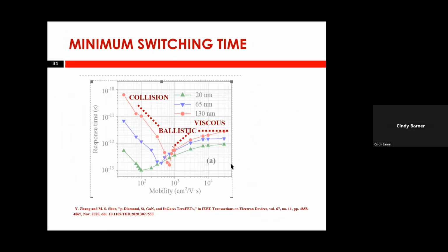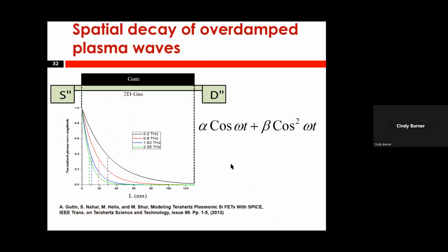And now, if scattering is too strong, then this plasma wave decays. But they take some distance to decay. They don't decay immediately. And this distance becomes shorter and shorter if you increase the terahertz frequency, because excitation immediately goes as a displacement current through the gate contact of the device. But what happens even in this regime, when you have no plasma waves, is the following. If you shine terahertz radiation on this device, the wavelength of this radiation will be much larger than the device dimensions. It would be on the order of hundreds of microns, if not a millimeter, 300 gigahertz at 1 millimeter. And devices have micrometer dimensions even taking contacts into account.